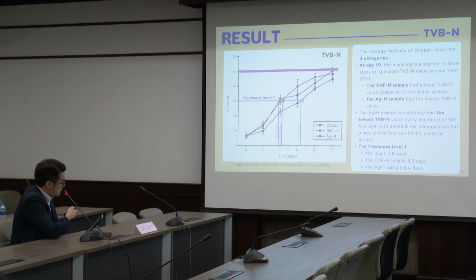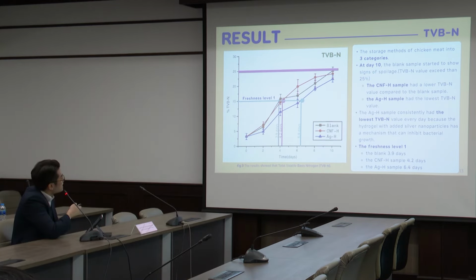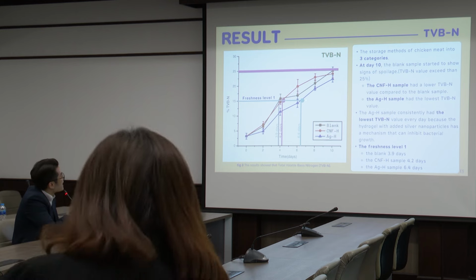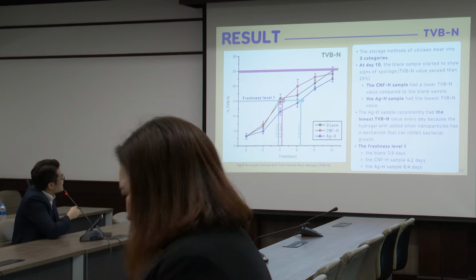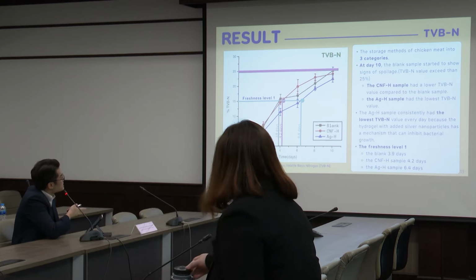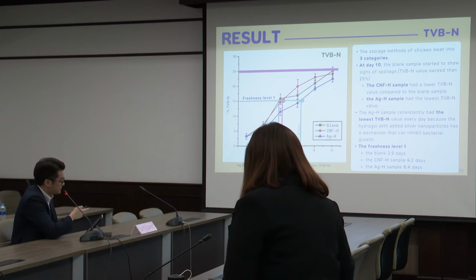And if we consider freshness level 1, with a TVBN value lower than 15, it shows that the blank has a shelf life of about 3.9 days and CNF 4.2 days, and the best condition is the Ag-H, which has the longest shelf life of about 6.4 days.